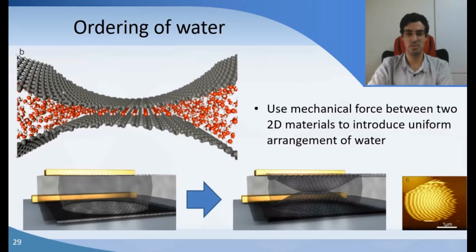Water is forming layers on any kind of surface, and normally these layers are fairly thick. Water is not self-limiting in its adsorption. But what we're doing is we're applying a mechanical force between 2 layers of graphene, and so we're squeezing out the excess water. We thought we squeezed out everything, but we're going to get back to that. So we're squeezing out water by nano-electromechanical drum structures. Both of the layers are getting in contact, and they're forming this very tight interface.